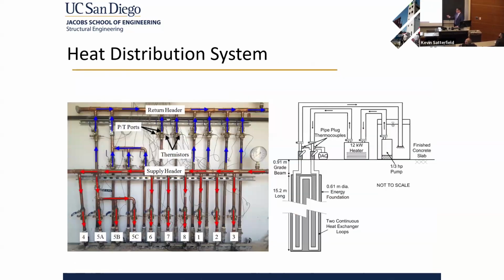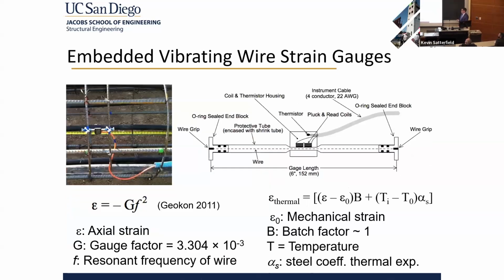So we made a nice mechanical manifold where we had heat going in one side and then the cold fluid coming out the other. We did some simple thermal response tests where we had a pump that circulated hot water through the pile, and we measured the temperature and flow rate going in and out. And then we had our vibrating wire strain gauges at different locations along the pile.